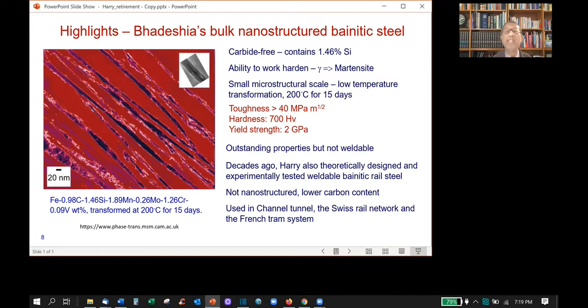But more than 20 years ago, Harry also theoretically designed and experimentally verified a weldable bainitic rail steel that is also free of carbides. This is not nanostructured. It has much lower carbon content. Depending on the grade of the alloy, it can have about 0.3 weight percent carbon, more than 1 weight percent silicon, some amount of manganese, and other alloying elements such as molybdenum.